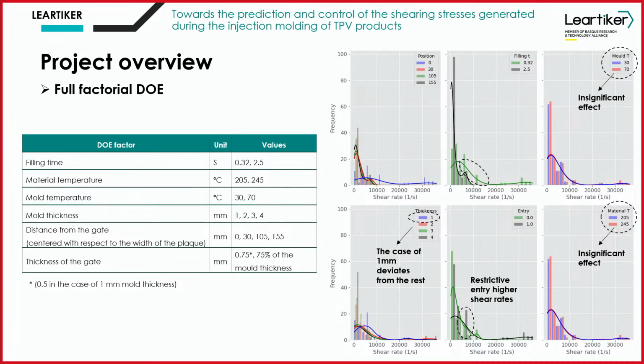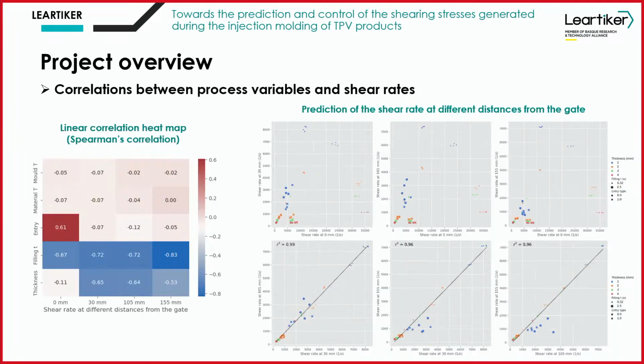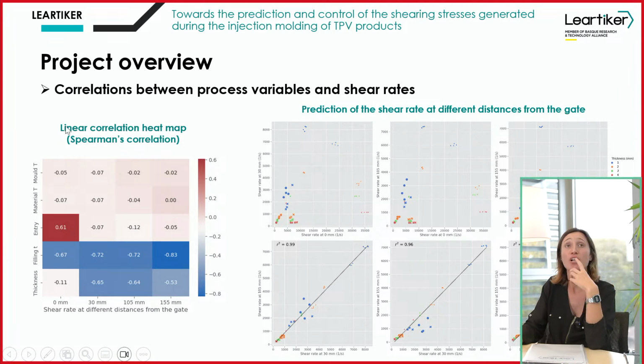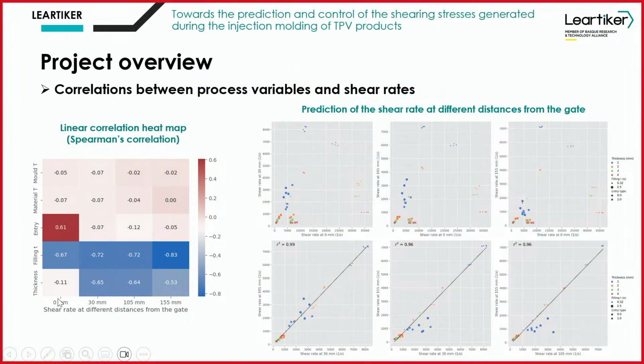So this was a first approximation to the effects, but in order to go more in depth into the correlations we can have between process variables and shear rates, we also analyzed the linear correlation heat map, or the Spearman's correlation, in this case, to see how the process parameters can influence the shear rate at the different positions. So this is important because at the end, in a component, we want to analyze how locally the different process parameters may induce the shear rate in order to better optimize the geometry, the design locally. So here what we can see is that if we are in the gate, then the entry is the one that is affecting more.